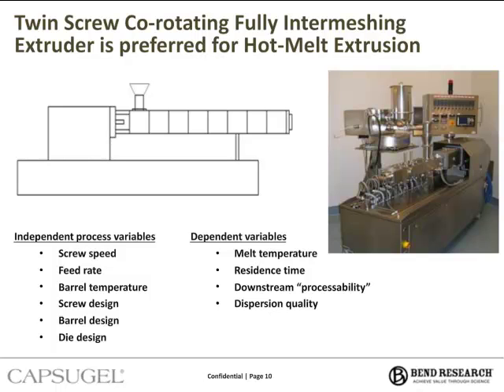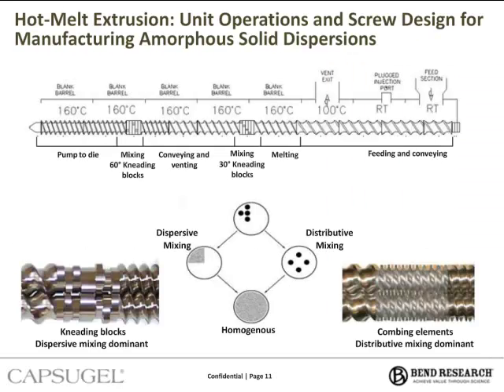Now what makes extrusion so versatile is that you can have multiple unit operations in a single extruder. The barrels are heated and cooled independently, and the screw has removable elements. So what this allows us to do is to design a barrel temperature profile and a screw design that allows us to achieve our goal, in this case, manufacturing amorphous solid dispersion. So on this slide, we show a typical setup for our screw design and for our barrel design.